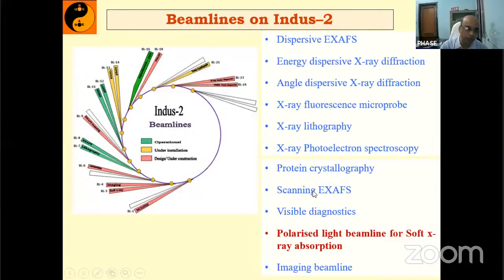Then scanning EXAFS. You know that materials are normally present in two parts, basically crystalline materials and amorphous materials. For crystalline materials, we normally use the X-ray diffraction technique. But for the amorphous material, you don't know how to characterize that kind of thing. So that is basically the EXAFS, X-ray absorption fine structure. Here one can get the near neighbor information, and from this near neighbor information one can find out what kind of structure is there inside the sample. So for the amorphous sample one can do the EXAFS.